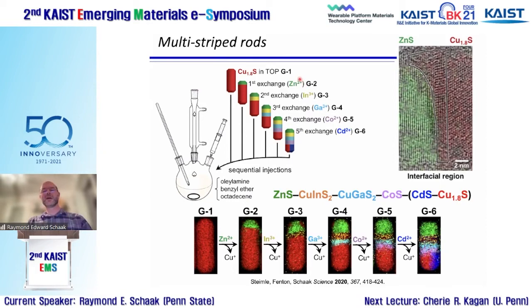What I mean is we use a specific volume and concentration of a zinc 2 plus exchange solution to exchange, let's say, something like 1/6 of the copper cations in the copper sulfide rod. So what happens is you just get a part of the rod that exchanges. So it's the effect of introducing a zinc sulfide tip on an otherwise copper sulfide rod.